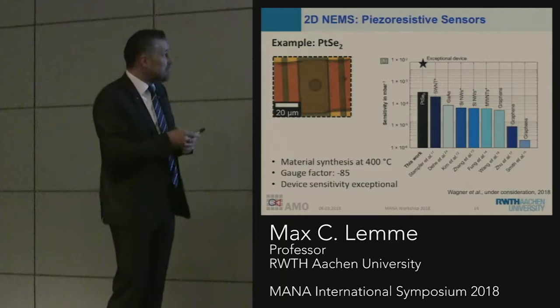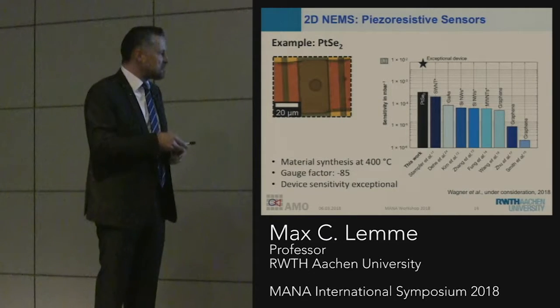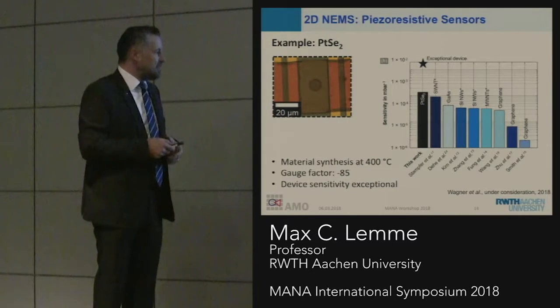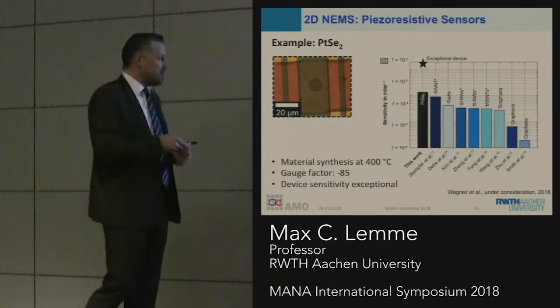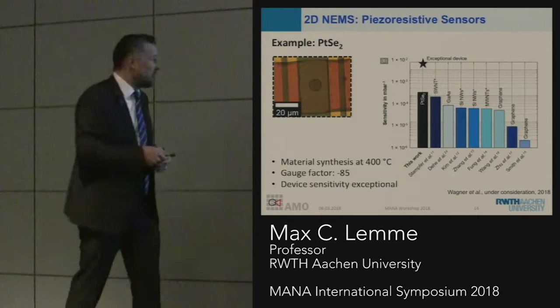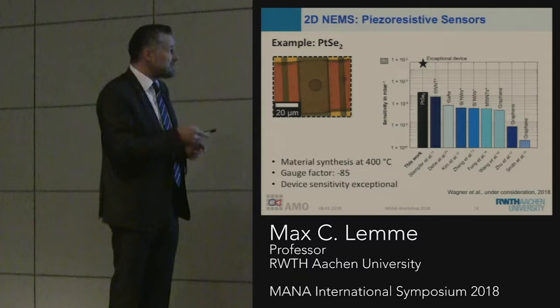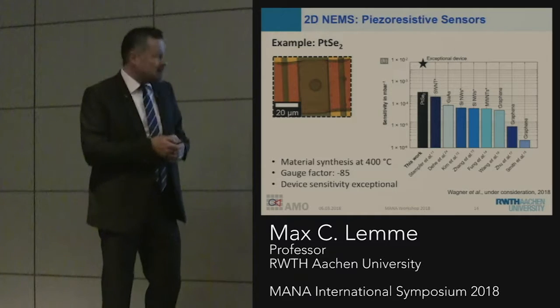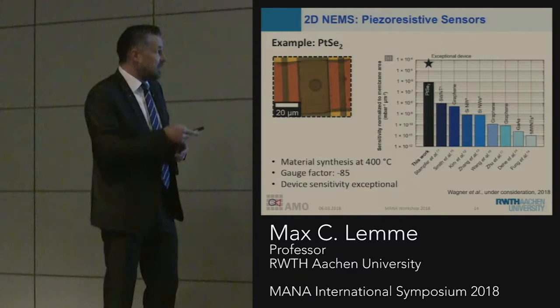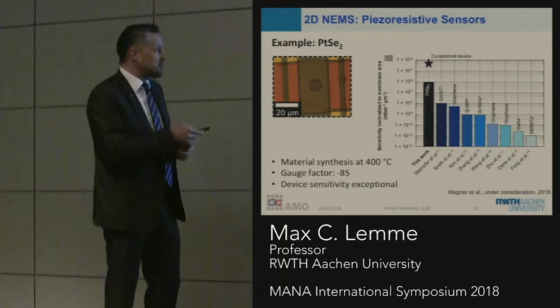So we also did this with platinum diselenide, and here the gauge factor is -85. So at the end of the day, this material would be an even better strain sensor. Again, the sensitivity is already better than even commercial products which are optimized for sensitivity, but if we normalize this again, the advantage is at least 2 orders of magnitude.